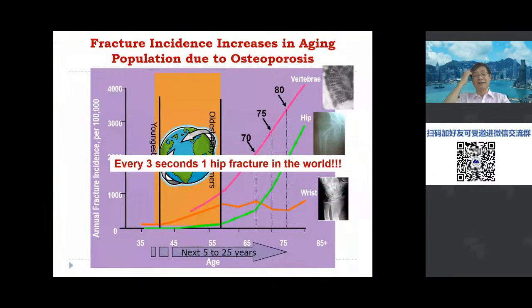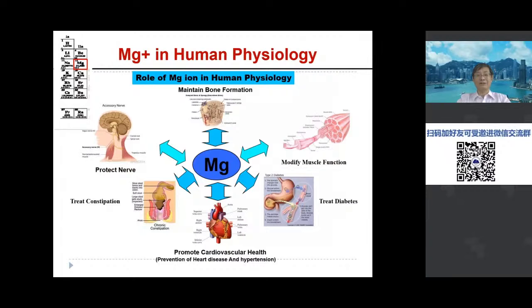So the idea is how to develop a new material for aging people, for osteoporosis. Every 3 seconds, there is one hip fracture in the world. And with increasing age, the risk becomes higher and higher. The problem is if you use traditional implants, such as titanium or stainless steel, we quite often need to do a second operation to extract the plate and other supporting elements. So the idea is to develop a biodegradable structure. So what's the composition? It's magnesium based.